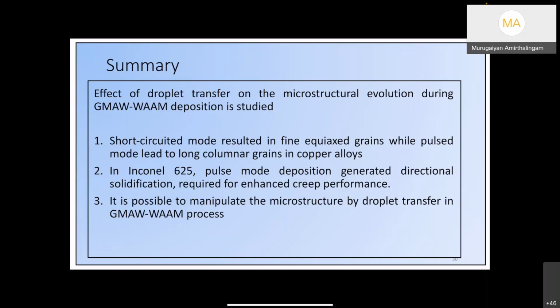I gave several examples, right? So a forging tool, for example: if you decide to make it by additive manufacturing and it fails within one use, what is the point in using additive manufacturing? So the lesson you need to take is to understand the physics of the process, so that you can control the microstructures and get the mechanical properties. And we show that the additively manufactured components outperform the conventionally made components in terms of mechanical service, because of the controlled microstructure we can generate with very fine equiaxed grains. So therefore, additive manufacturing becomes attractive.